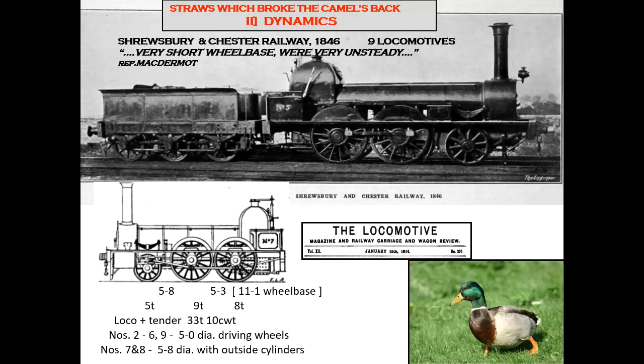Now, early steam locomotives had a tendency to yaw, rather like a waddling duck. In other words, a long body and short legs close together. A main reason for that was that there was no counterbalancing in the wheels in those days; the oscillating effect of the cylinders hadn't been dealt with. There were no counterbalance weights. So therefore there's nothing to stop, under the action of the cylinders and the pistons operating, this yawing action in plan.